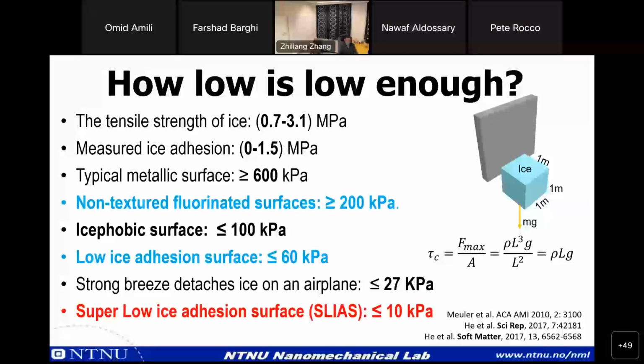In addition to the low ice adhesion surface, we have a so-called super low ice adhesion surface. If you have one cubic meter of ice, and it can fall down automatically by its own weight, the ice adhesion strength is approximately 10 kilopascal, and we call this value super low ice adhesion. This was one of our targets, to develop surfaces to achieve this kind of value.